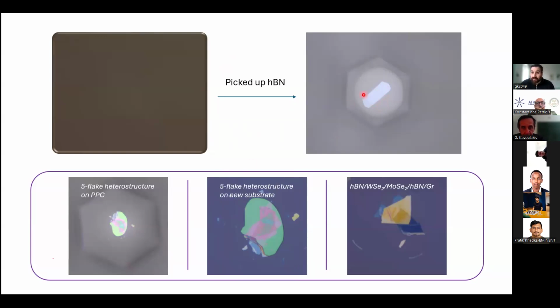And we tested that not only for one flake, but for several flakes of different thicknesses. You can see a 5-flake structure on the apex of the pillar here. And we managed to successfully transfer it on another substrate with no problem and no debris. And on top of that, of course, this is just a test sample, but we managed to use the same protocol to create a full heterostructure containing HBN, monolayer TMDs inside, and a gate and a graphene that we can come and do lithography and contact. So this is a rather promising technique and a rather promising customized tool.